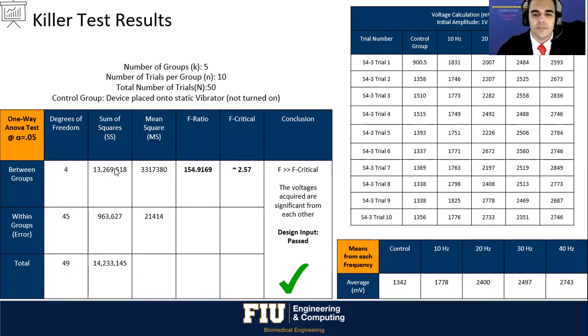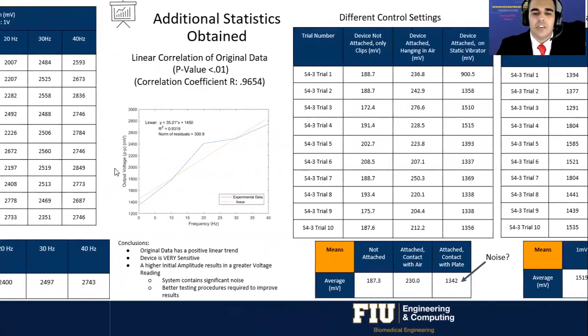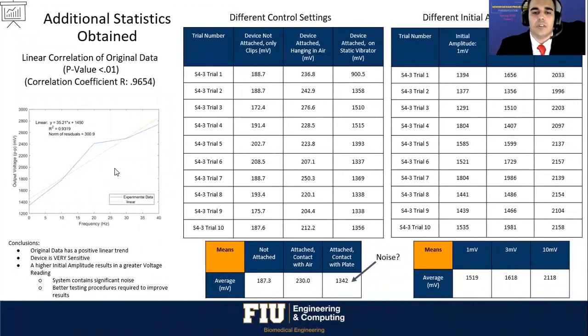However, we dived deeper and wanted to see if there was a correlation between the frequencies and initial amplitude set by the function generator. Using linear regression, we were able to identify a strong positive correlation between the frequency the machine operated in and the peak-to-peak voltage that was being generated. A summary of the control data we as a team collected shows that the device is very sensitive. A positive trend was also shown when increasing initial amplitude voltage from 1 millivolt to 10 millivolts.